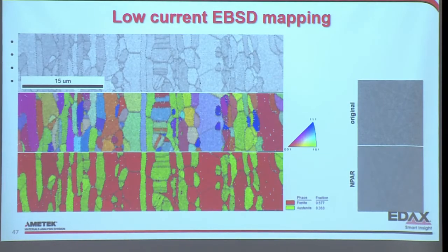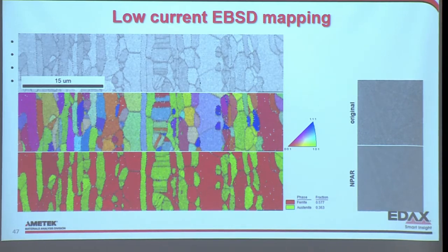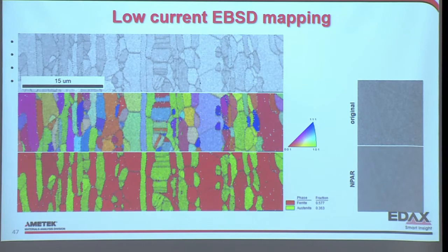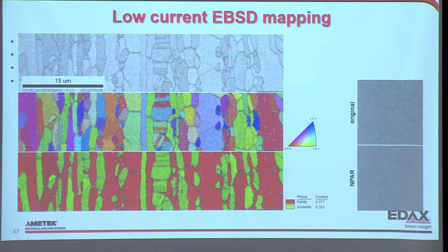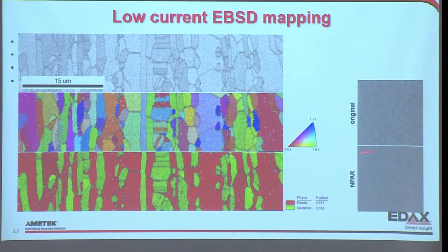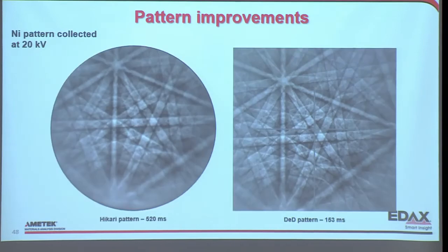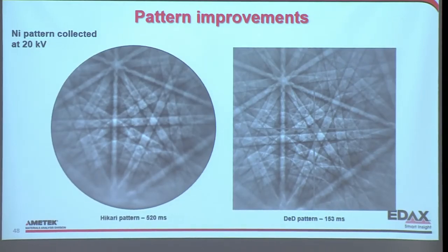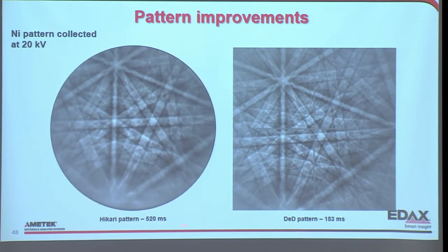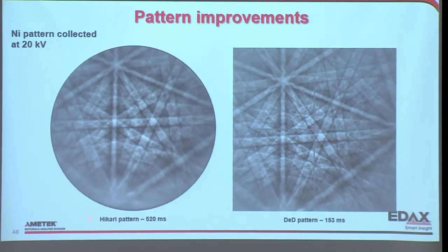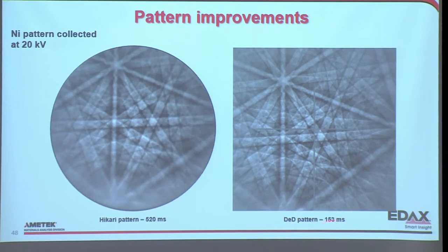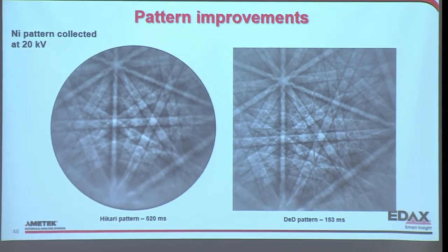So we can use this and do a scan. It's not anything to get excited about because that's really not our focus, but just to show you we can do it. And this is low current. Here are the patterns, and we've had to do something called NPAR to get it indexed. But just to show you the quality of these patterns, this is nickel at 20 kV. This is 520 milliseconds on our Hikari, our CCD camera. This is the direct electron at 153 milliseconds. And you can see the amount of detail here. You can see these kikuchi rings.